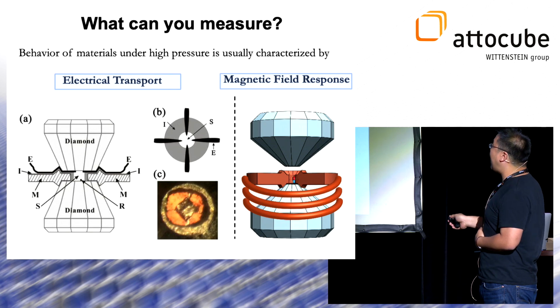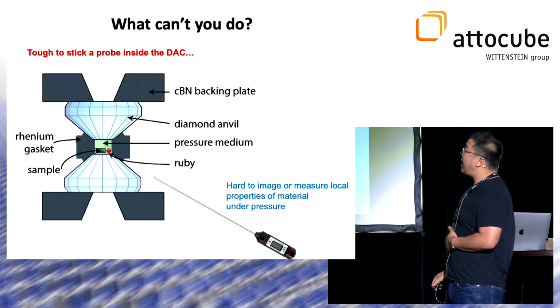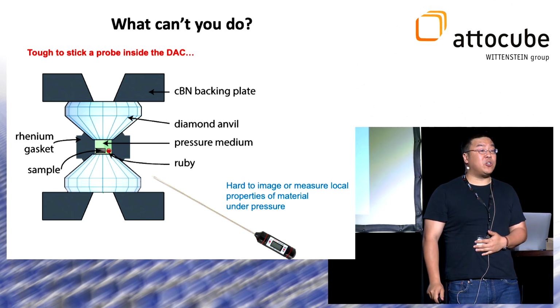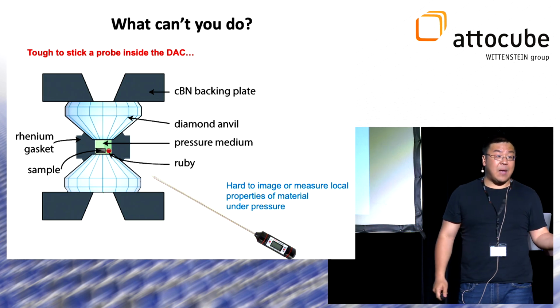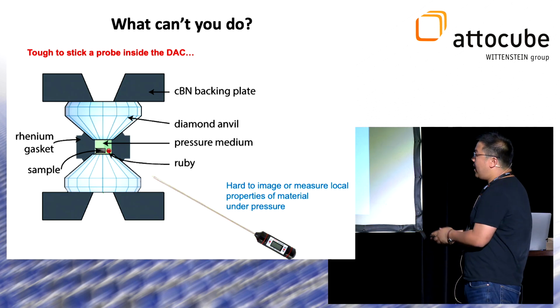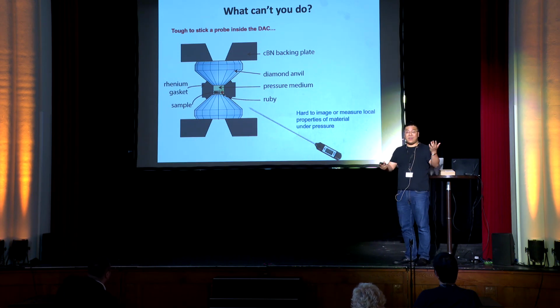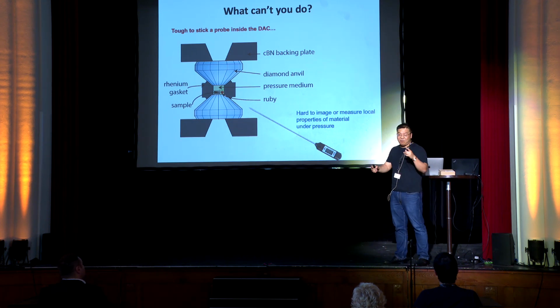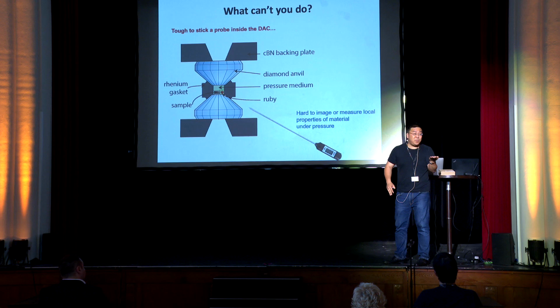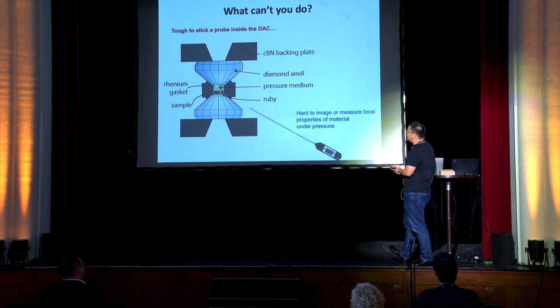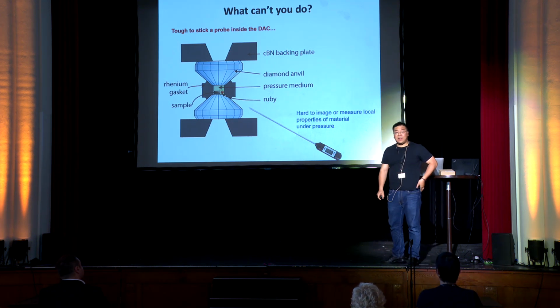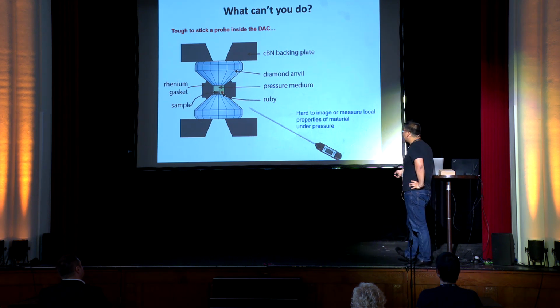So one thing you can immediately see about this type of geometry, in terms of measuring magnetic fields of samples at high pressures, is the challenge that I'd like to emphasize, which is that it's very, very tough to make local measurements inside a diamond anvil cell. I'm giving specifically the example of magnetism, but this is true more generally. It's hard to imagine sticking a magnetometer in. For example, Patrick Maletinsky and Vincent Jacques earlier in the week gave beautiful talks about using scanning tips or using defects in hBN to sense things. But it's quite difficult to imagine how I would stick a scanning tip into the high pressure chamber to actually make local measurements of magnetism at the sample. So one of the enduring challenges, something I became accustomed to from talking to my collaborators, is that it's very difficult to image or measure local properties, for example magnetism, of materials under pressure.